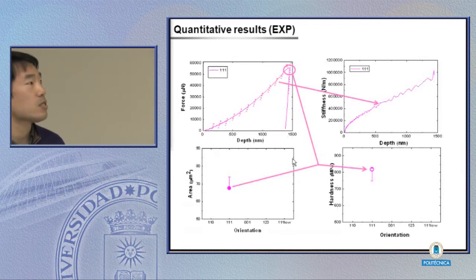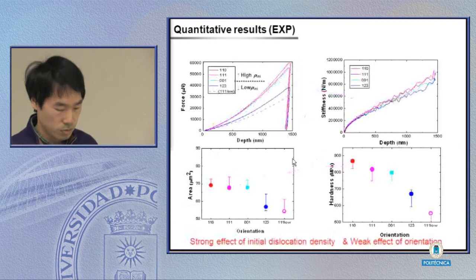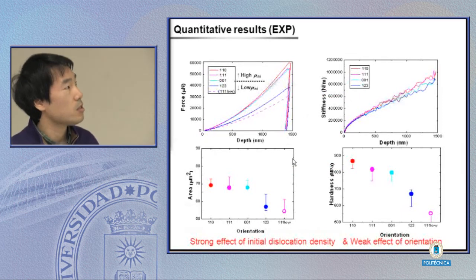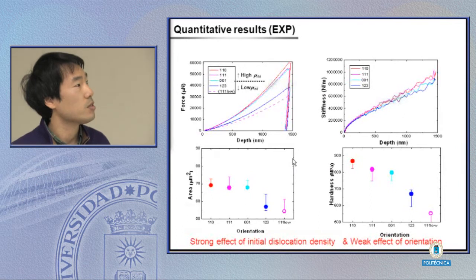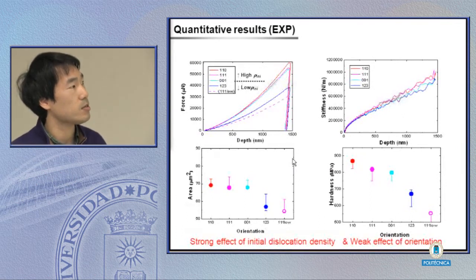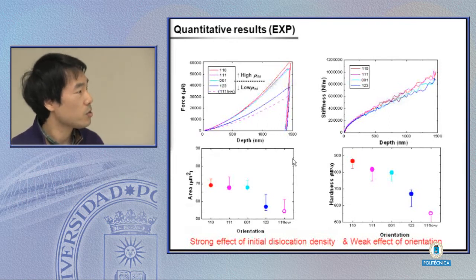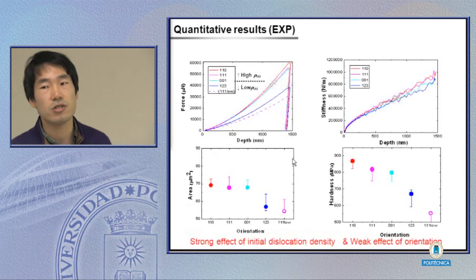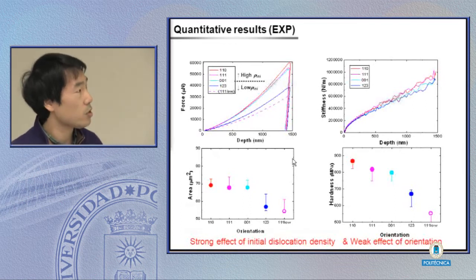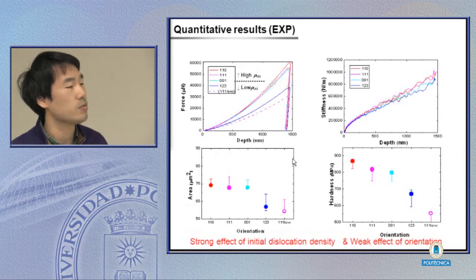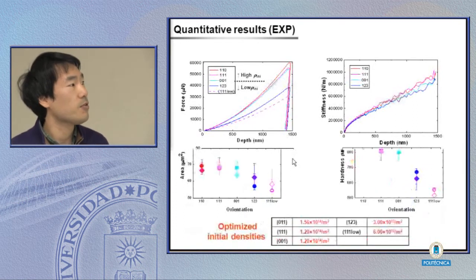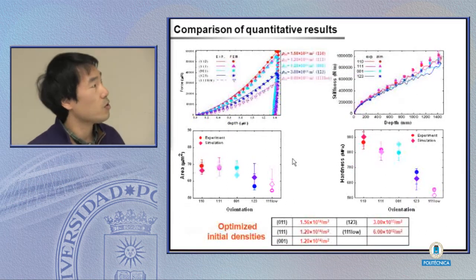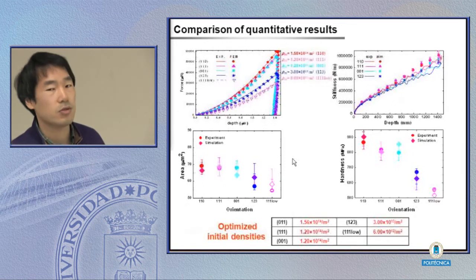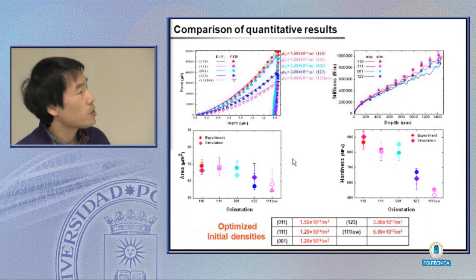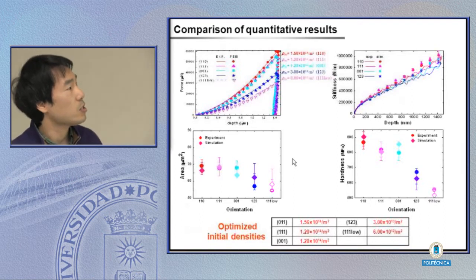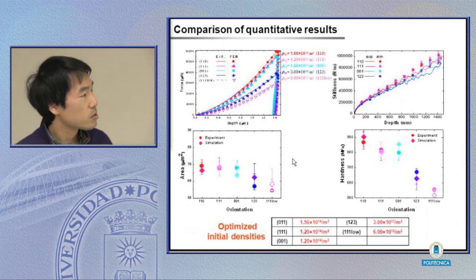Using this nano-indentation test, we can have the load displacement curve, and from the slope of the unloading curve, we can have stiffness data. And we also obtain the contact surface area using the FEM test, and using both the load displacement curve and the area data, we can have the hardness data. We do the same procedure for specimens with 4 different orientations and 2 different initial dislocation densities. As you can see, the load displacement curve and all the other quantities totally depend on the initial dislocation density.